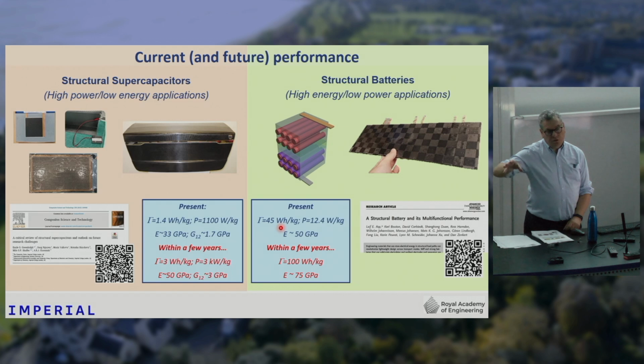If you remember, a conventional lithium-ion battery is 280 watt-hours per kilogram, but this is increasing rapidly. That's the number they've published. They're now up into about 100 watt-hours per kilogram in terms of their energy density. So we're getting very close to approaching a conventional battery or a conventional supercapacitor. But the added thing that we can offer is a capacity to store but also carry mechanical load. So we don't need to be as good as a conventional battery or supercapacitor in what we're doing.